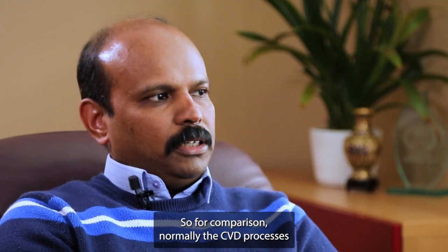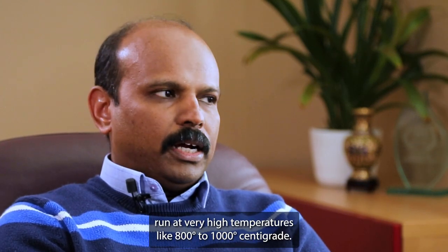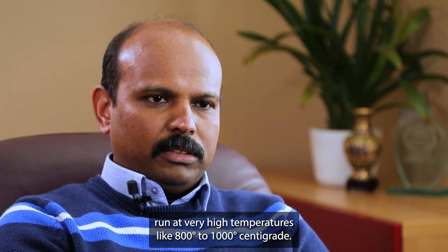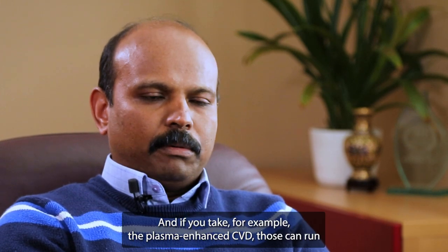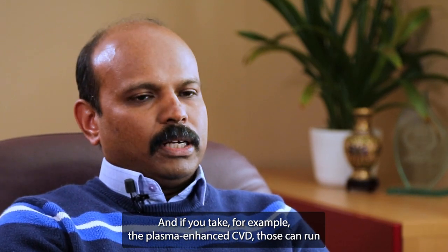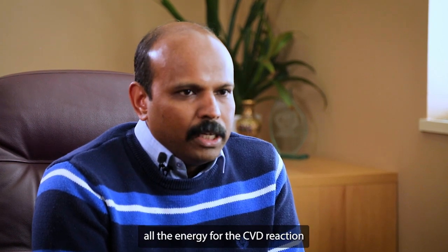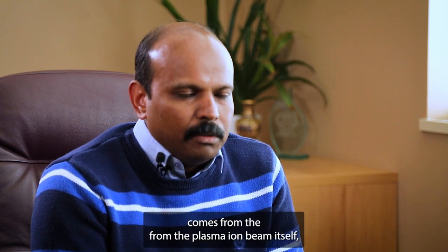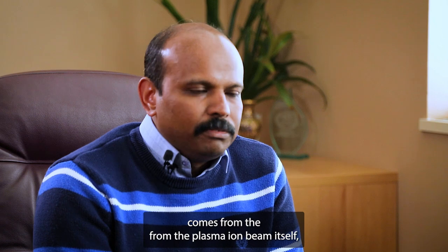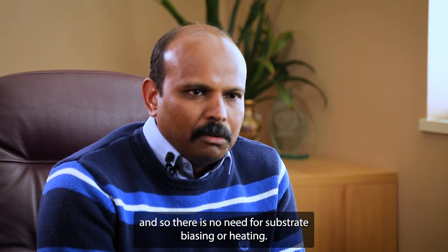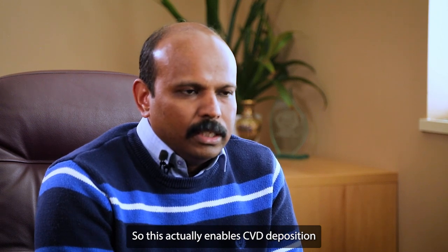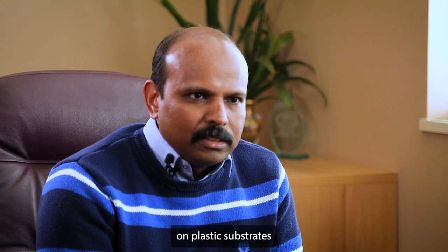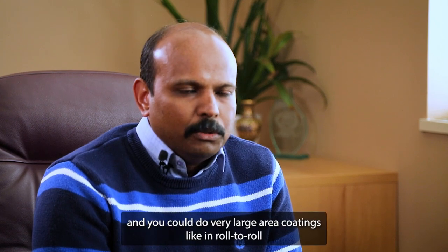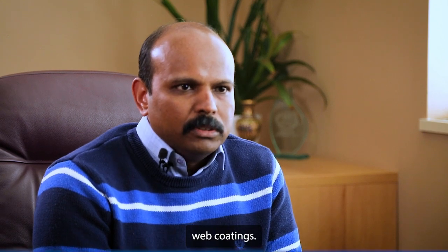For comparison, normally CVD processes run at very high temperatures, like 800 to 1000 degrees centigrade. If you take, for example, plasma enhanced CVD, those can run at lower temperatures like 400, but they still require substrate biasing. In the case of PIB-CVD, all the energy for the CVD reaction comes from the plasma ion beam itself, so there is no need for substrate biasing or heating. This actually enables CVD deposition on plastic substrates, and you could do very large area coatings like in roll-to-roll web coatings.